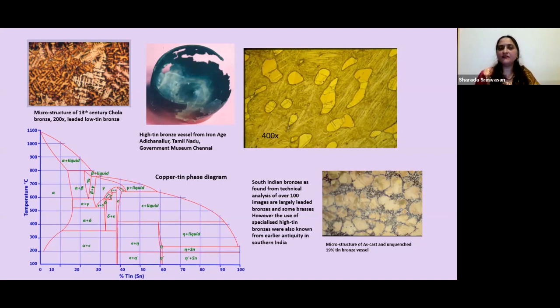And so you have these marvelous vessels, such as from Iron Age Adichanallur, which shows extreme hot forging to make these very thin rimmed vessels. And just to show you what would happen if those vessels were not quenched: on the top you see what has happened when such a vessel has been hot forged and then quenched, which means it's been very rapidly cooled in water. So you get the formation of this needle-like martensitic phase, which is really very important in terms of the ductility of the bronze. But if you hadn't quenched that bronze, then you would have had the formation of this bluish-white network, the alpha plus delta eutectoid, which is what embrittles the bronze. So the quenching prevents that.